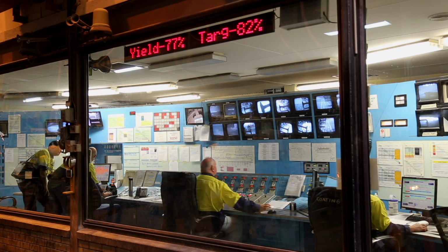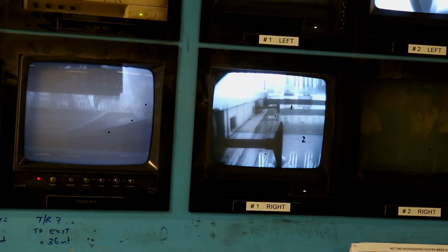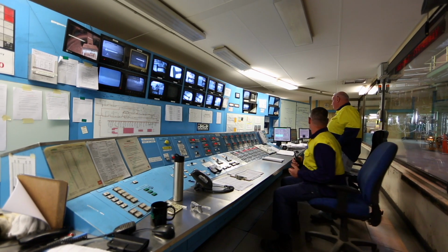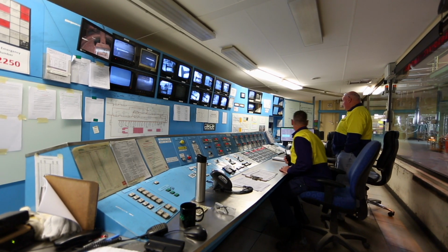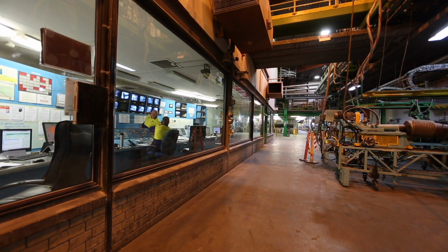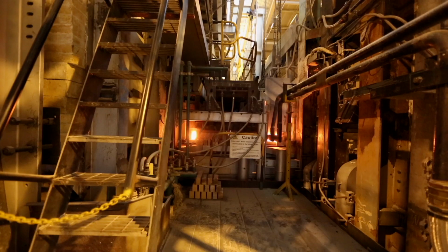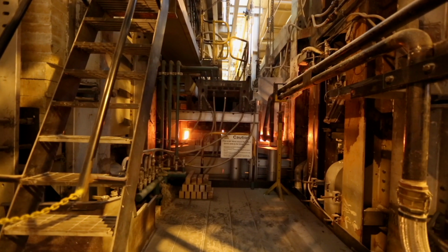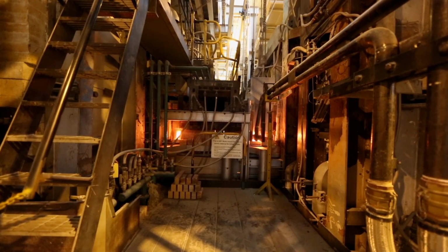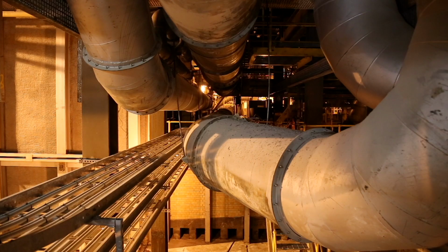With constant 24/7 monitoring of this process by the control room, this continuous ribbon is now being produced infinitely, varying from 2.5 to 12mm in total thickness. It can be up to 1000 meters an hour on really thin glass, down to as slow as maybe 200 meters an hour on the thicker substances. We're firing something in the order of 4,000 cubic meters of gas every hour in that furnace. So our gas bill is something in the order of $500,000 per month.